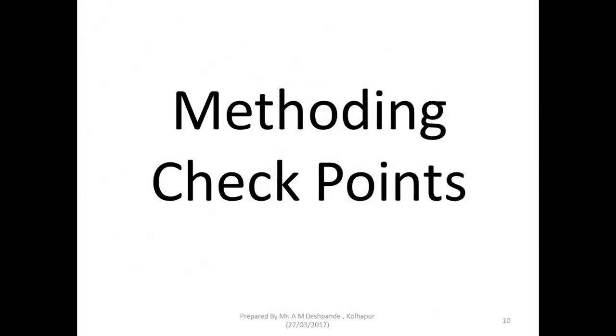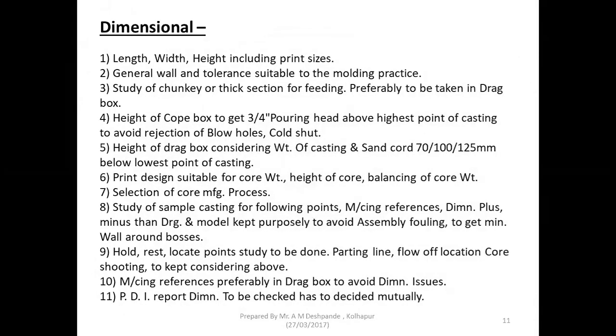These are the methoding points while designing the pattern and core boxes for APQP, advanced product quality planning. Length, width, height, including print sizes, general wall, and tolerance suitable to the molding practice. This is most important. If tolerance is plus minus 0.5 mm and machining allowance is 2 mm, then in that case we have to go for shell molding.